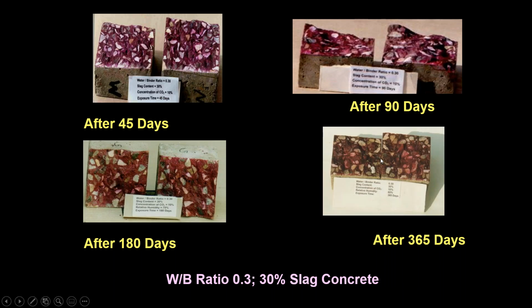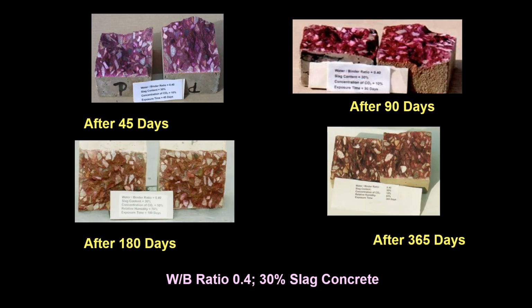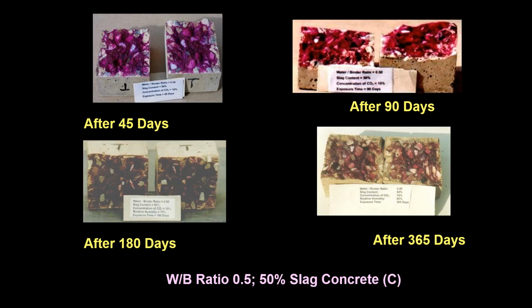Total. And this is the case of slag. I'll expand the cases where you can see water binder ratio 0.5, 50% slag. Yes, there is a carbonation on the edges. You can see at 1 year.